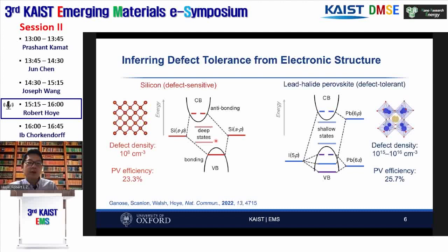And the only way to get around that is to get rid of the defects as much as possible, which is why it's so important to process these at high temperatures and have very high purities. Now contrast that to the perovskites. We have a very different electronic structure. And this time, the original atomic orbitals are close to the band edges rather than being in the middle of the band gap. So when you form point defects such as vacancies or interstitials, there's a much greater likelihood that your defect states will either be resonant within the valence band, or if they do form within the band gap, they're much more likely to be shallow rather than deep.